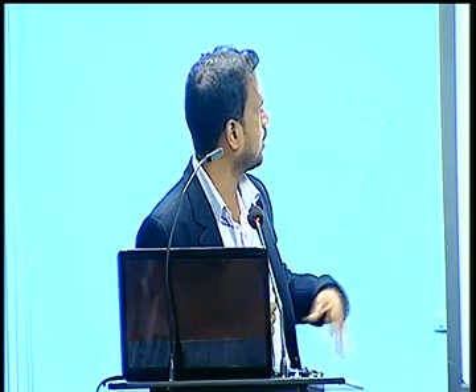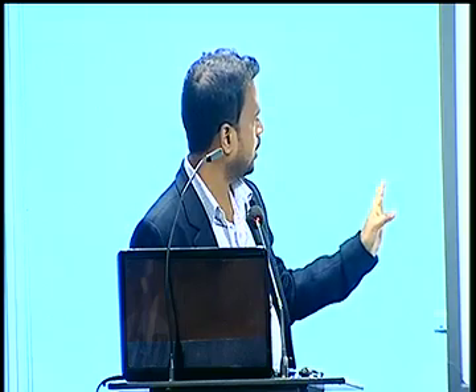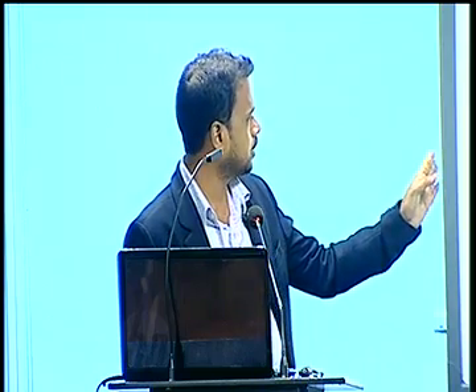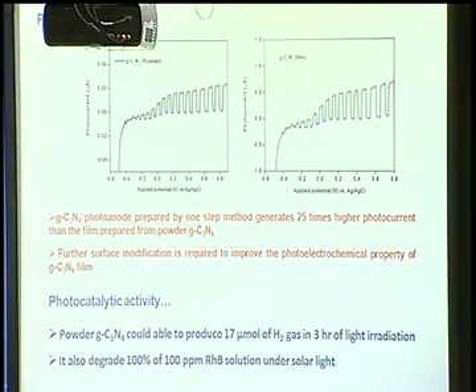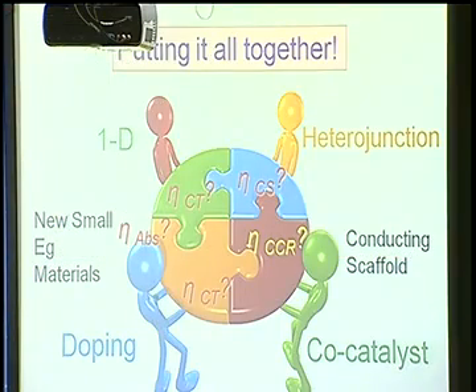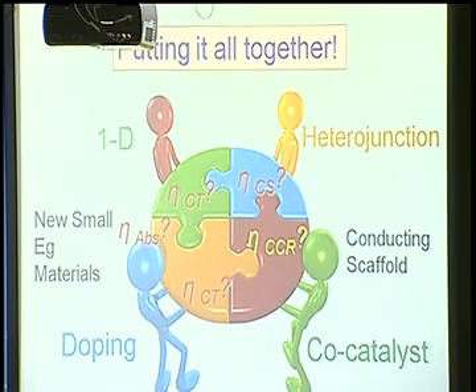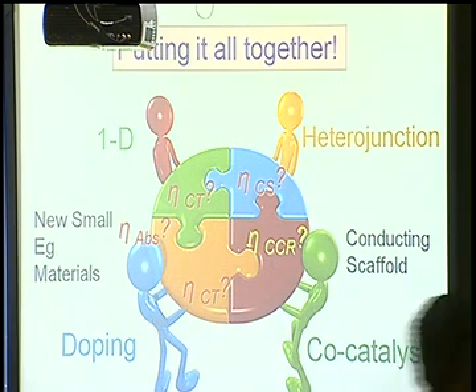When I tested the powder catalyst for photocatalytic activity, it retained its own activity. It could generate 17 micromoles of hydrogen gas in 3 hours of light irradiation, and also degrade 100% of a 100 ppm Rhodamine solution. So, putting it all together, in order to design an efficient photocatalyst, we have to look towards heterojunctions. Also, we have to add a conductive scaffold like graphene, and also utilize co-catalyst doping.